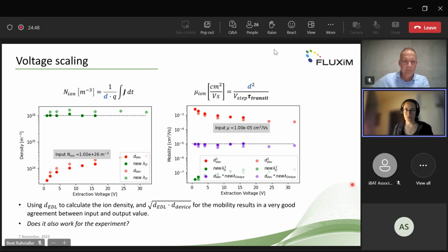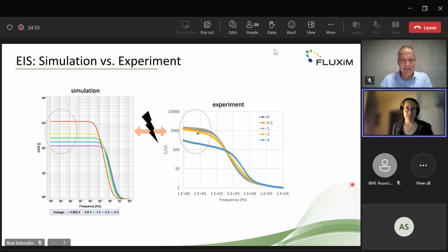We're very happy, and we wanted to try whether this also works in the experiment. And Moritz now tested it. And well, the first thing we tried was to look at the impedance spectroscopy data plotted in this capacitance frequency. And you can already see that when we change the DC voltage in the simulation, we get a lot of variation in the capacitance over more than 1 order of magnitude, while in the experiment, this low frequency part did not really vary that much. So there was also already a first indication that this probably is not the full truth.